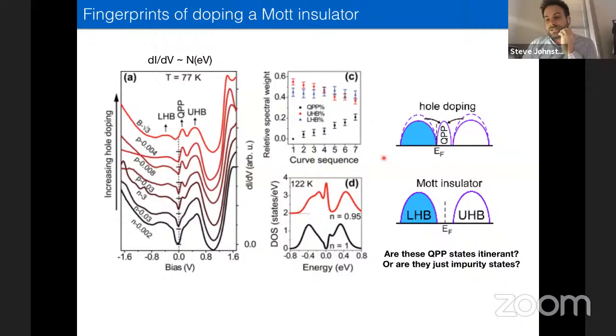Now, this is unfortunately not conclusive evidence. Again, we would have liked to have seen a more clear trend in the weight of the lower Hubbard band. There's also any number of reasons why you might expect states to form in the gap, right? You could imagine that there would be impurity states forming from the boron. Any number of things could be happening. And so this now comes back to the DQMC calculations I showed you. If this is really a quasiparticle band, we expect this peak to have a dispersion, right? There should be a dispersive state.